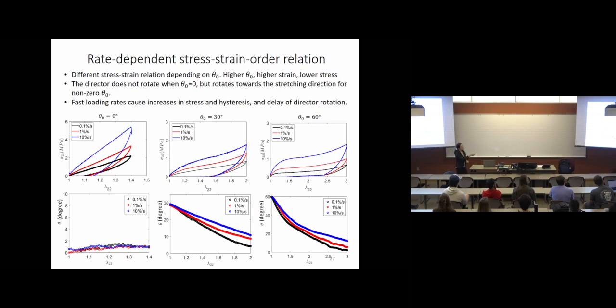Moreover, we also see high rate dependency, not only for this previously reported stress-strain curve, but also for this microscopic director rotation. When you stretch it very fast, we observe a delay of the director rotation.